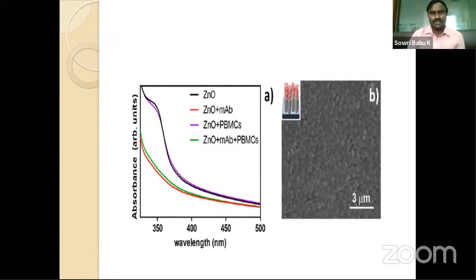So you can see here, generally zinc oxide has an absorption peak at around 360 nanometer. First, we tried to attach PBMCs directly to the zinc oxide, and we took the absorption spectrum. There is no change in the absorption peak of the zinc oxide. That means PBMCs are not attached to the zinc oxide. So directly we cannot attach PBMCs to the zinc oxide.